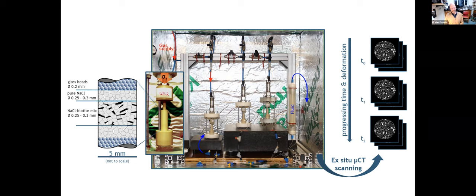This is halite. Then there's mica in specific configurations. That's a biotite. And then there are some salt glass beads, just to maintain permeability into the sample. These are then loaded into this rig here. These are straining frames, we call these, so essentially they cannot move anywhere. And this is a pneumatic ram, an actuator. They're screwed into the top plate here, connected to a pneumatic system. So we pressurize that, and then a stamp comes out and presses down onto these from above, as you can see here. There's a system to control the pore fluid.